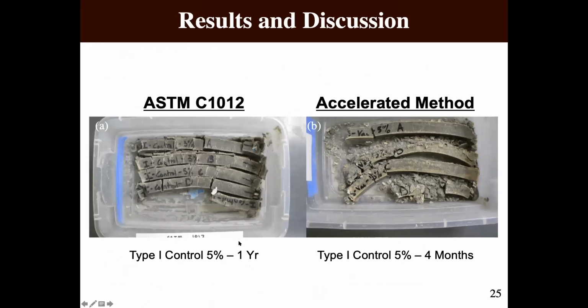So I kind of wanted to show the sort of deterioration as well. You can see here on the left, the 1012 method versus the accelerated method. This is after 1 year, you have cracking, obviously breaking of the bar, but after only 4 months, complete deterioration with the type 1 control. So obviously showing the aggressiveness of this test method.